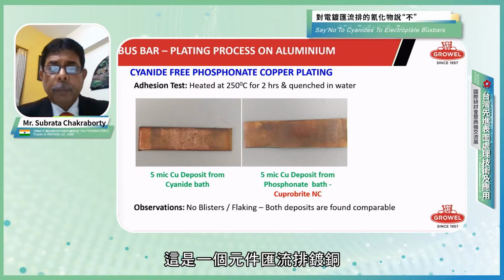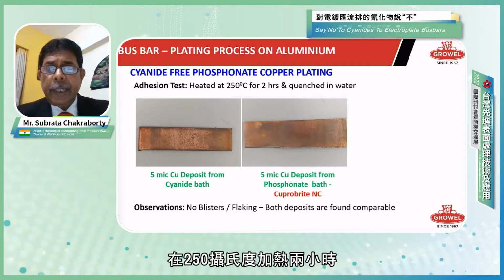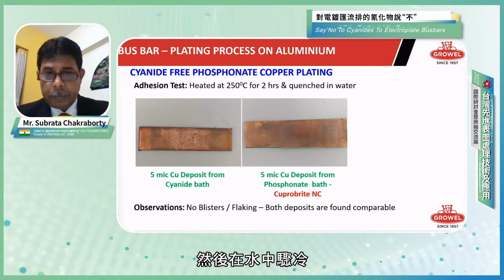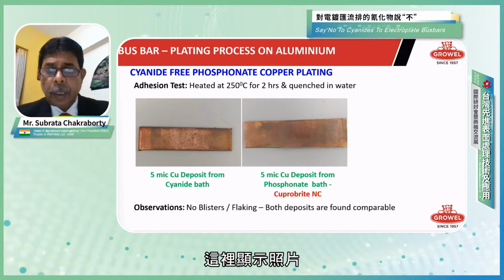This is a component, the bus bar, copper plated, and then subsequently heat treated at 250 degrees centigrade for 2 hours, and then subsequently quenched in water. The photographs are shown over here.